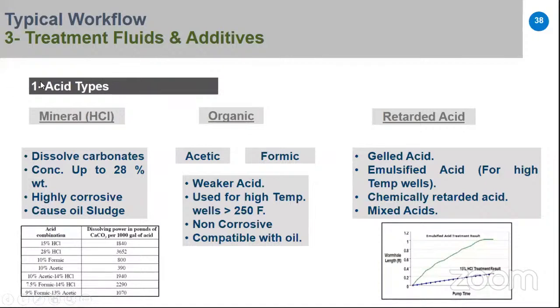So the first thing in our treatment fluid is our acid type. We have many types of acid. The first one is mineral acid, HCl. This is able to dissolve carbonate. It has concentration up to 28% by weight. But the disadvantage of HCl is that it's highly corrosive and causes oil sludge.